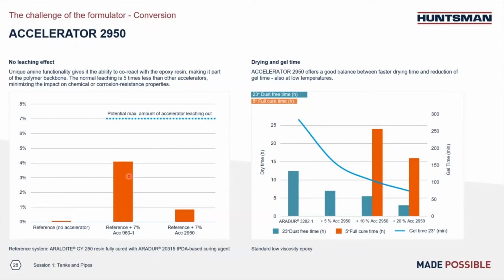So in formulation 2, with 7% accelerator 960-1, which is an industrial standard accelerator, we can see the leach out is more than 4%, right? And considering we add only 7% into the total formula, that means about 60% was leached out. If we look at formulation number 3, with accelerator 2950, we're only seeing leach out of less than 1%, which means only about 10% got leached out, right? So with this kind of minimized leach out, it won't compromise the system performance, such as chemical resistance or corrosion resistance.